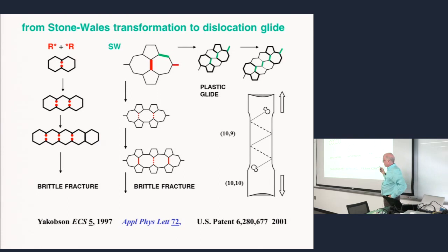And then, of course, we know from materials, from crystal physics, that this is a topological defect. Topological defect in the sense that if you have a contour in your lattice and you go around it, you get a misfit after you complete your contour, you get a Burgers vector. So this thing is characterized by a well-defined topological invariant called the Burgers vector. That's important because then you look back at the nanotube, and although I don't talk about nanotubes, I rely on the fact that all of you know that they have chiral symmetry and are characterized by chiral indices, these two numbers, like a social security number for nanotubes, N, M. (10,10) would be metallic, (10,9) would be semiconductor and whatnot. And (15,0) is a semiconductor with a different band gap, and there are different rules.